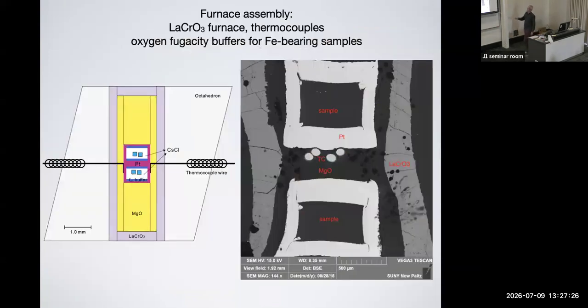Right, here's a schematic of one assembly that we used. This on the outside, right? So this white here is that MgO, that octahedron. Here is the lanthanum chromate furnace and parts. That's so you conduct electricity, it's resistance heating. You conduct electricity through that. This is what it looks like after the experiment. The nice thing is, right, this has been at 27 GPa, and I don't know, the sample at 2,000 Kelvin or something like that.